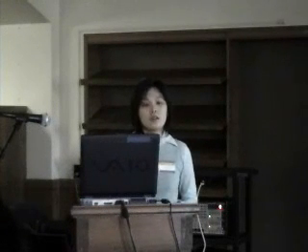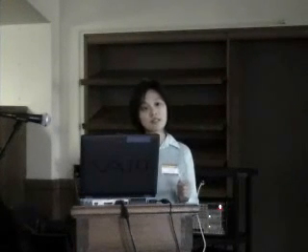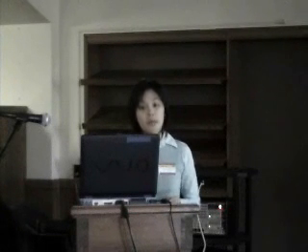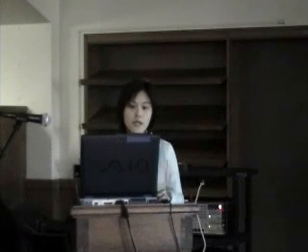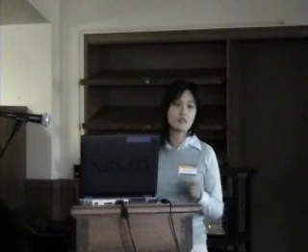So in summary, we synthesized in-house quantum dots which are biocompatible, and this quantum dot fluorescence is pH dependent in both aqueous solution and in fixed cells. And its behavior is monotonically increasing with increasing pH. And we also observe the pH-dependent photoluminescence of quantum dots in living cells. And its behavior is similar to the traditional pH indicator. But quantum dots are not sensitive to photobleaching, so this demonstrates our quantum dots have potential to be used as an intracellular pH sensor.